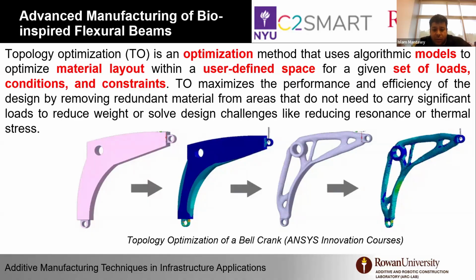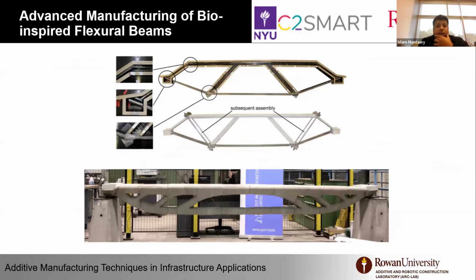You can see here from ANSYS software the process on the metal side, where you can see the left side cantilever can be optimized to use much less material and have the same performance, even better than the original one. The process is not invented by us. It's been in the literature for years, and people are using it to optimize different structures. Here's work at Ghent University in Belgium, where they 3D printed a shorter bridge, and it was segmentally printed and connected together using post-tensioning.